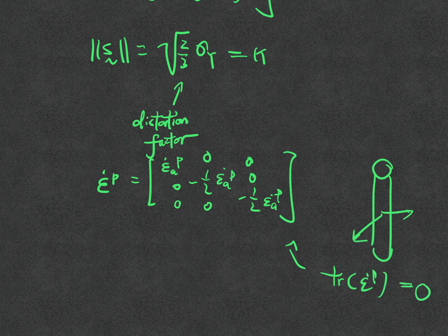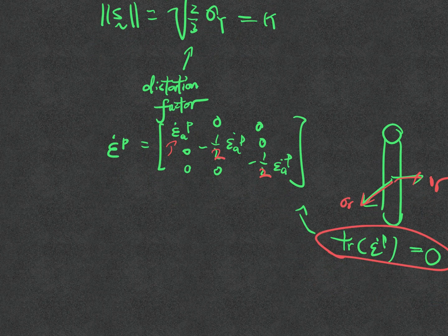So the only way to make this constraint and this symmetry fit is to split that total amount in half. Epsilon dot p 22 and epsilon dot p 33 should be identical, split by half, and when I add the diagonal components together, I get nothing. That fulfills my goal of having no plastic volumetric deformation. Now go back to the business.